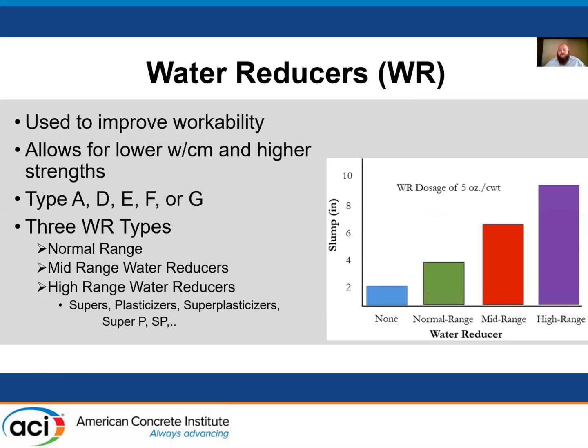If we're just doing conventional concrete, maybe you have a neat mix that doesn't have any admixture. Maybe it has a 2-inch slump, but if you add a normal range water reducer, you might get a little bit higher slump. If you add a mid-range water reducer, you might get an even higher amount. And then if you add a high-range water reducer, it'll become even more. This is just an example of adding 5 ounces per 100 pounds of cementitious weight, something that you might get for a mix.